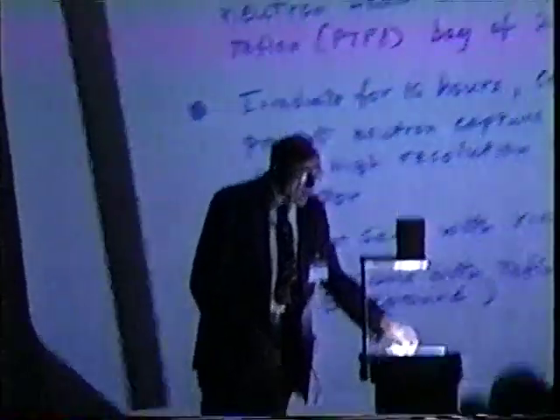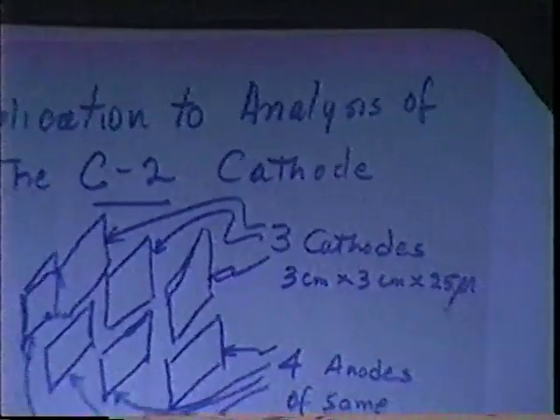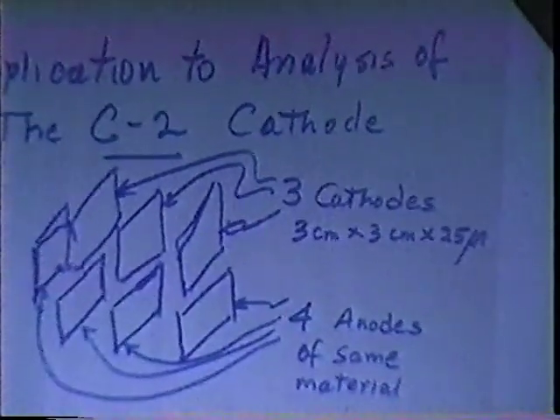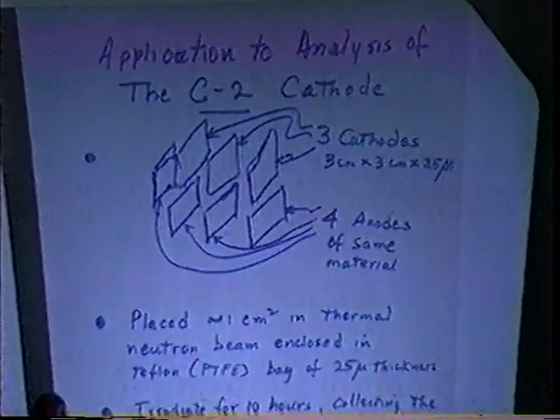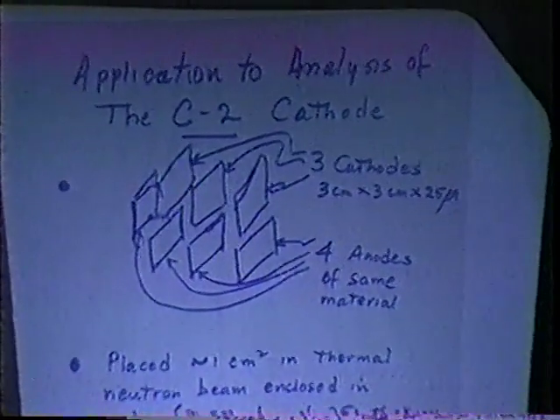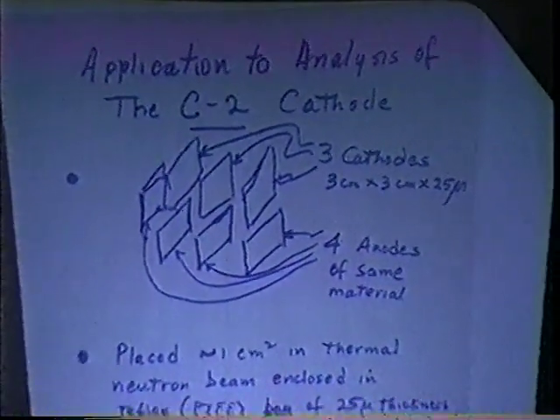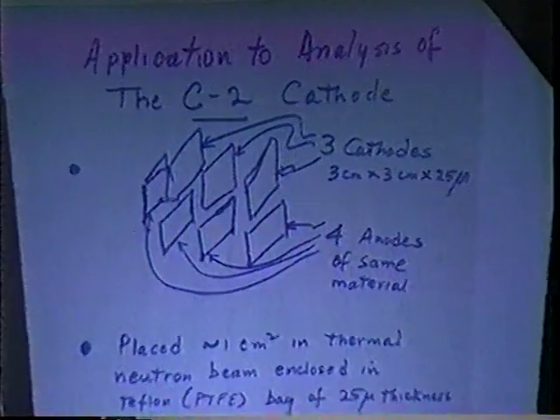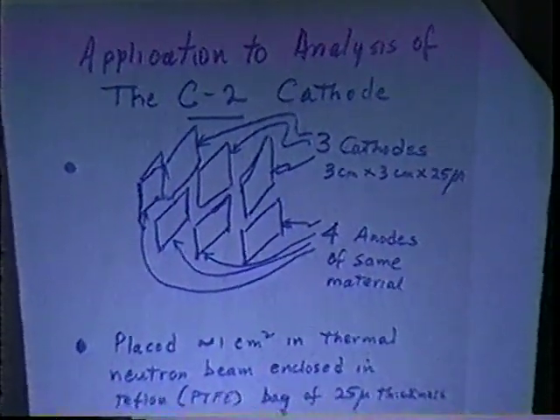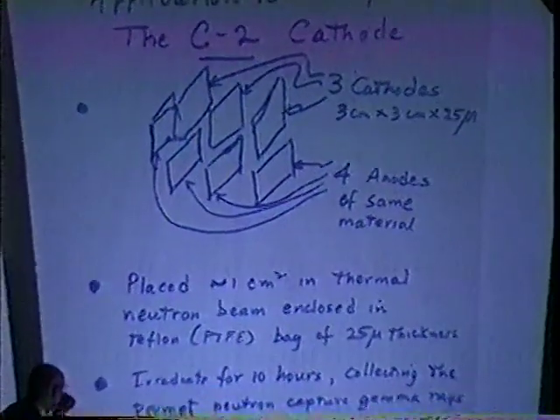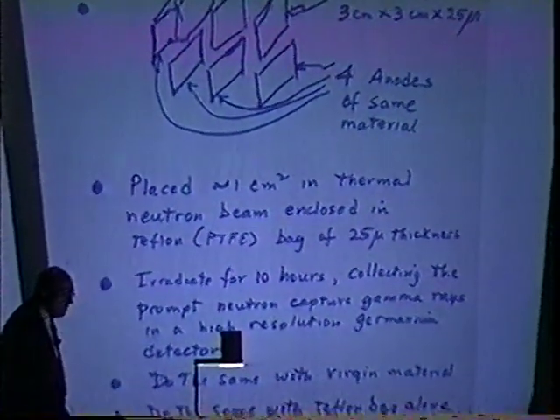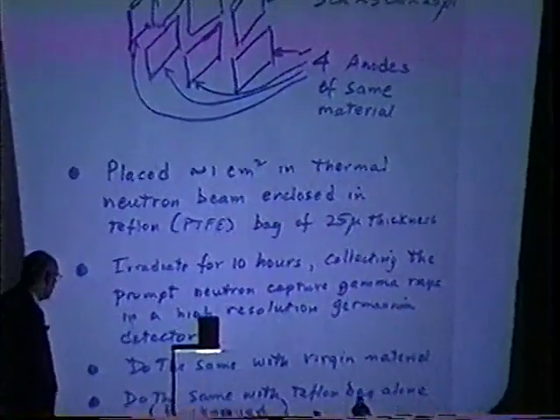But the fact that we don't see neutrons and tritium to any degree with heat led me to think that some other reaction might be the actual heat producer. Now, I've crudely shown the cathode that I chose, a C2 cathode from the SRI work. The cathodes were three in number, interleaved with four anodes, about a square inch of material, a sort of multiple plate condenser geometry. And I took a square centimeter of the cathode, which I hope is representative, and placed it in a thermal neutron beam